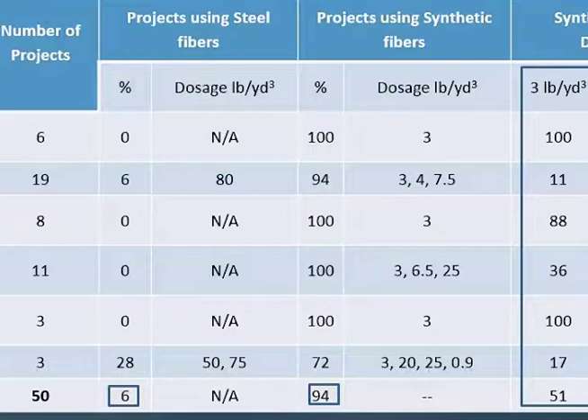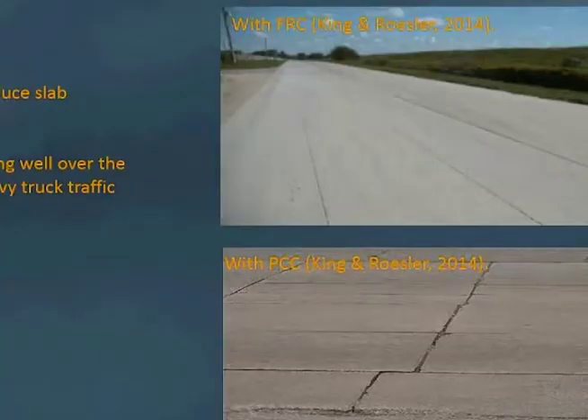Some responded according to the residual strength ratio criteria. So we have used fibers, and we see a lot of pictures showing they are performing, but we really do not know if 3 pounds per cubic yard is really the optimum dose or not. So we investigated a little bit on that too. And these are some pictures sent to us, or we collected from different published reports or papers.